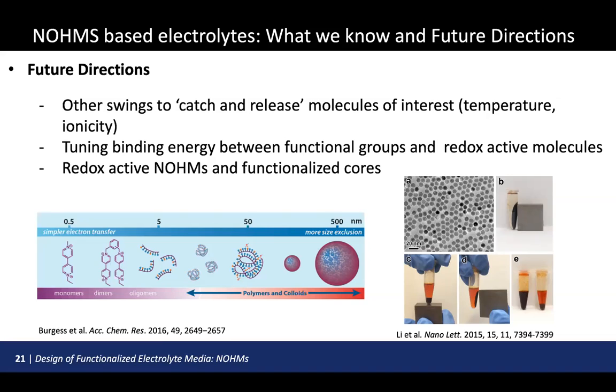So hopping, I think we do think it's happening, but it really depends on the competition between hopping and the binding energy and so on. That's what Tony and Sara are looking at, and what Sara talked about in one of her slides was adding salt, which competes not only with the proton or cation but also the redox active species. There's a lot of competition for the binding sites, and depending on that, things going in and out of these functional groups are very different. Very interesting phenomenon, as long as you don't add too much salt and coagulate the nanoparticles.